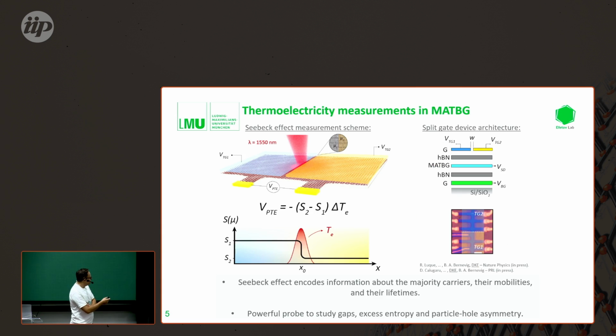So to do this, we devised some thermoelectric measurements. In particular, we wanted to measure the Seebeck effect in these TBG devices, where the Seebeck effect is sensitive to the majority carriers. It's sensitive to electron-hole asymmetries. And this is a good measurement technique to sense this particle-hole asymmetry in these devices.